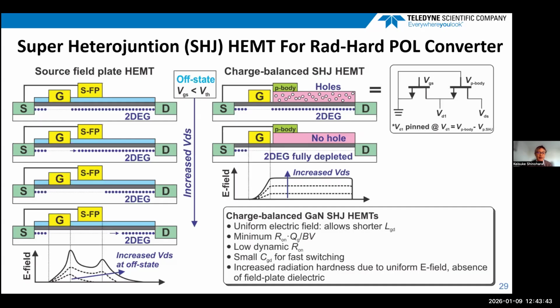And also the uniform electric field allows us to achieve low dynamic R-on, and it minimizes the gate-to-drain capacitance, which is important for fast switching. And in addition, the uniform electric field increases radiation hardness because it is known that a single event defect is caused by the high electric field point. And this device doesn't have the field plate dielectric as compared to the source field plate, and the absence of such a dielectric minimizes the SEDR, single event dielectric rupture, which also helps to improve the radiation tolerance.